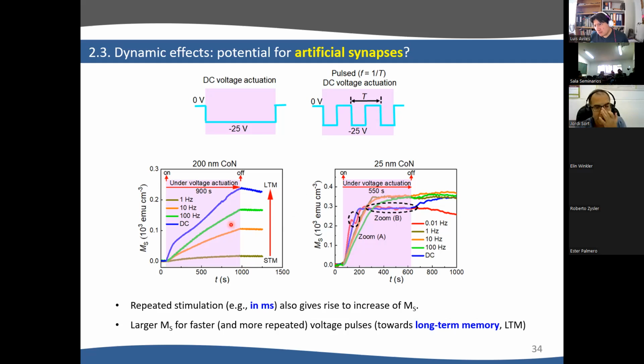So this frequency behavior is analogous to what happens in the brain, and it's called spike time dependent memory, and it shows a transition from short-term memory to long-term memory after repeated impulses. Now we want to understand why, if you go slowly, it doesn't work very well, right? And I will show this with the results for the 25 nanometers, where again you can see that the faster you go, the larger is the magnetization.